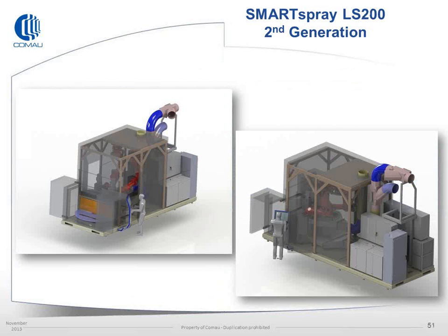The first one that you saw on the previous slide was a single torch system. This is a dual torch system. What you can see is that we've changed the suction system to a very large cross path, and it helps reduce and capture more of the dust that's collected. We've also had to move the inspection station below, as well as add some trap doors. It allows us to help capture and limit the exposure of the table to any buildup.